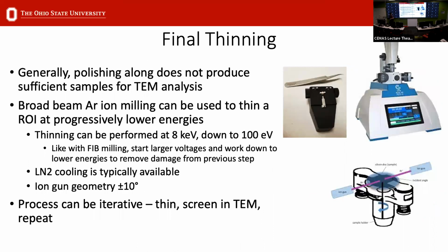This is the type of system that's commonly used for that, where you would clamp your sample into a holder like this, and you would focus the beam on that region of interest. A system like this one can perform thinning from 8 kV down to 100 V. Just like mechanical polishing and tip polishing, you want to work your way down from higher energies to lower energies to remove any damage that you're causing from previous milling steps.